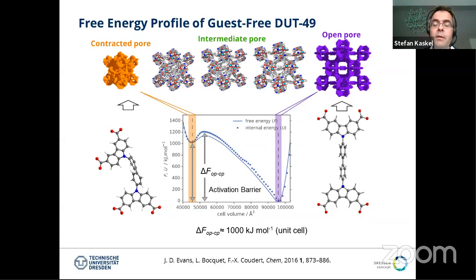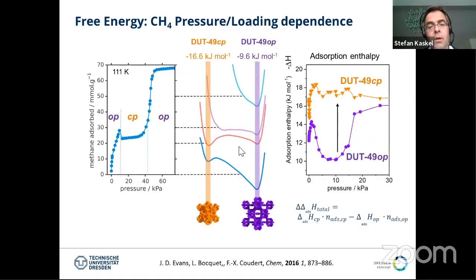Now, what happens when the gas is present? The gas basically compensates that. And Jack Evans calculated these bistable profiles for various gas loadings. And what you see is that with zero loading, the OP phase is the more stable one. But once you reach an intermediate loading, then the CP phase becomes the more stable one. So this local minimum becomes the global minimum in this case. And then at higher loading, again, the OP phase becomes the thermodynamically more stable phase. So at full loading, the OP phase becomes the more stable phase. And the reason for this behavior are the stark differences in adsorption enthalpy for the OP and the CP form. Because in the OP phase, you have a low adsorption enthalpy, and in the narrow pore or CP contracted pore phase, you have a high adsorption enthalpy in terms of magnitude.